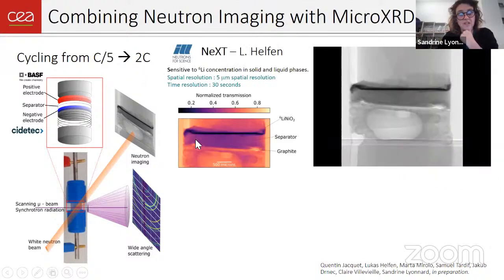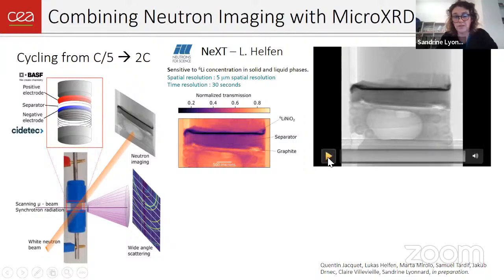So if we look at the first experiment, this is neutron imaging. Very nice experiment because neutrons are very sensitive to the presence of lithium, while X-rays do not really see lithium as such. And in addition, we had isotopically substituted lithium. We only had lithium-6 in our batteries, so it's enhancing the attenuation of the neutrons. And you can really nicely see the stack of the battery. So you have here the positive LNO electrode that is containing the lithium-6. It's very dark, this is this black line. In the middle of the two electrodes, a separator that you hardly see, and some graphite that is empty for the moment. And what happens when you cycle, you will see lithium ions going from the positive to the negative during the charge and then discharging back to the positive.